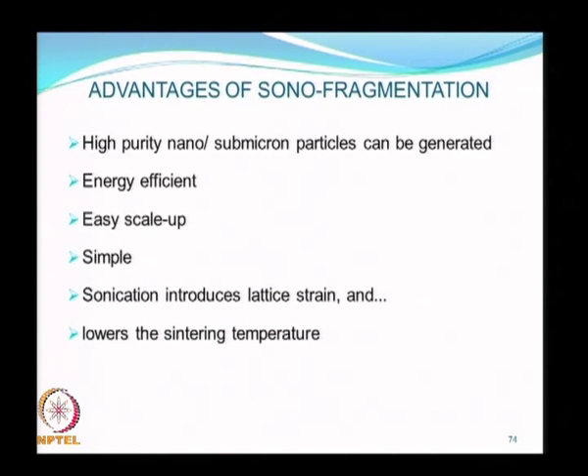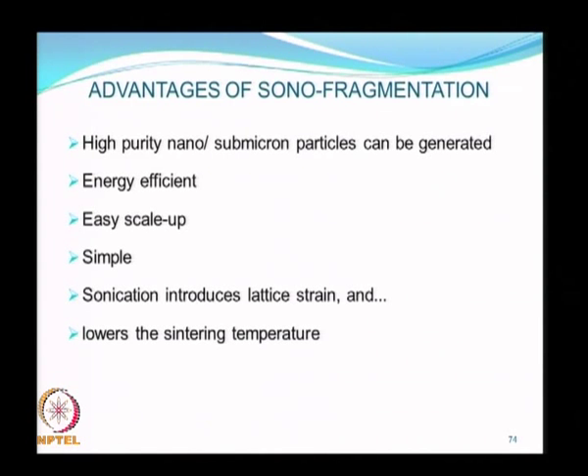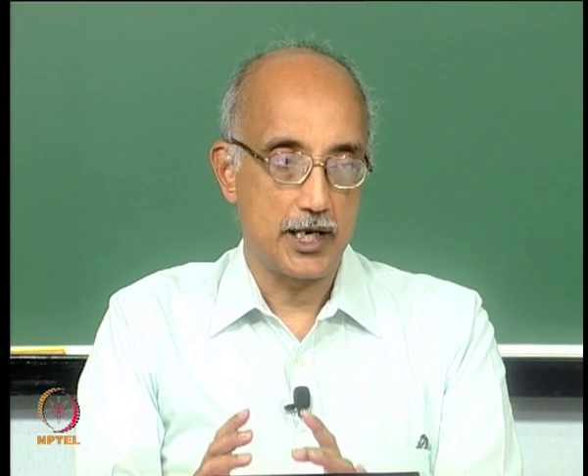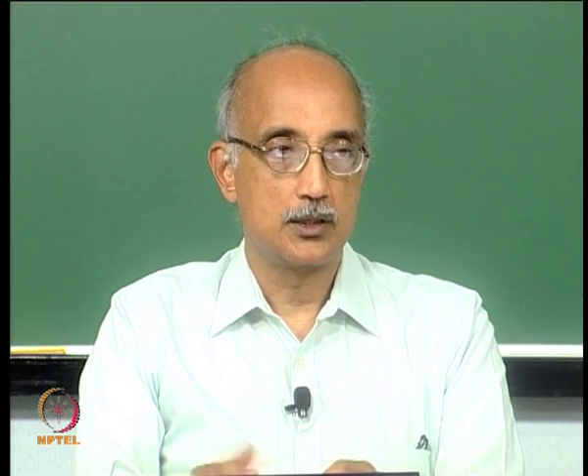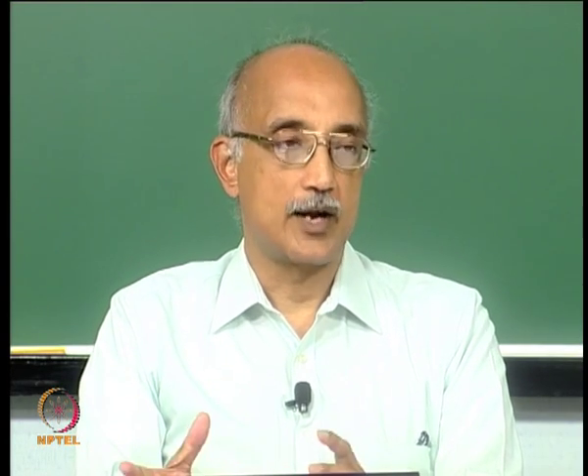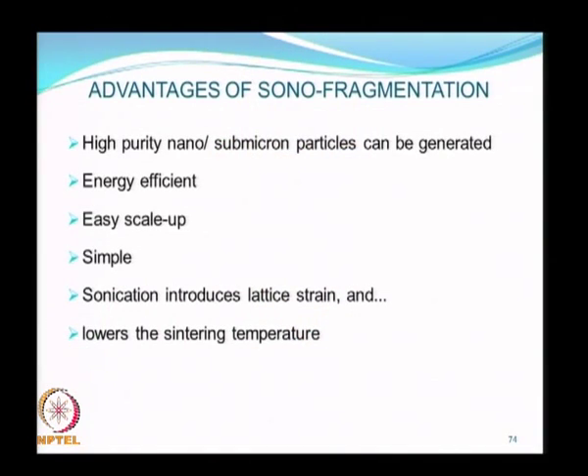Some advantages of sonofragmentation for synthesizing nanoparticles include high purity—no additional chemicals are involved; you simply use micron-sized feed material in high purity water, turn on the acoustic field, and fragment the particles. It is a simple, energy-efficient, easy-to-scale-up process. Sonication also introduces lattice strain into the crystalline structure, meaning the crystallinity of the particle is maintained and it does not become amorphous with extended exposure unlike high energy ball milling.